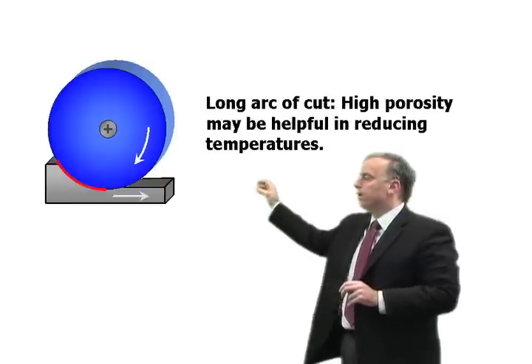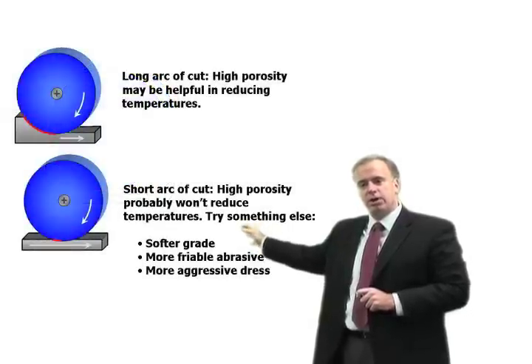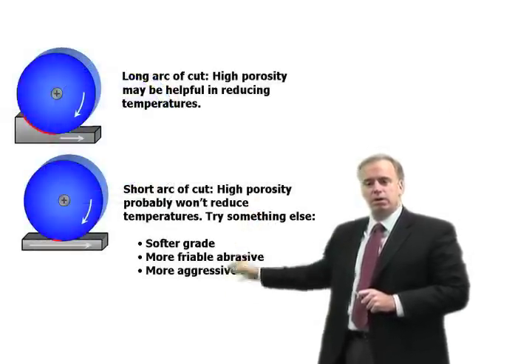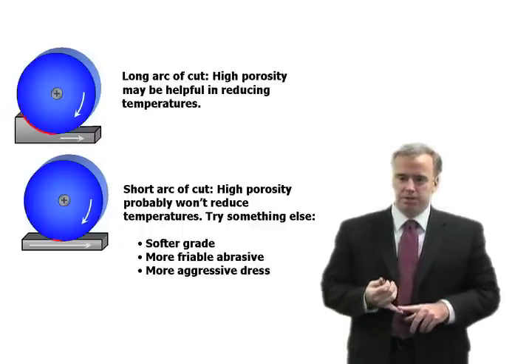So to answer your question, if you're doing creep feed grinding, yeah, you might see a benefit if you switch to a high porosity wheel. If you're doing surface grinding, shallow cut grinding, OD grinding, you're probably not going to see much of a benefit in a high porosity wheel.